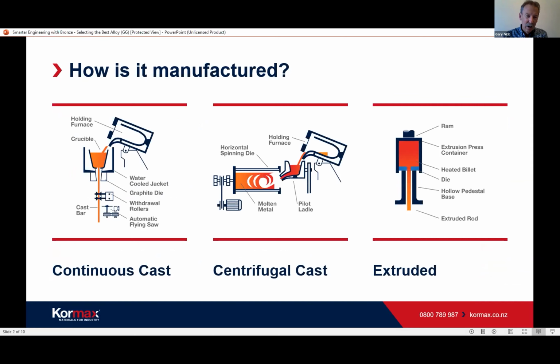Now, this is not all the ways that it's manufactured. This is what we do at AW Frasers in Christchurch. We do continuous casting, which is the one on the left, which has a distinctive striped appearance to it. If you notice a bar, it has stripes along the length of the bar. They're just surface marks, no bearing on the material, just from the cooling and the oxide layers on the outside. This process can do both hollow tubes and solid rods.